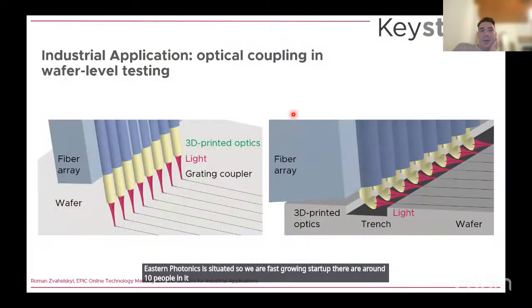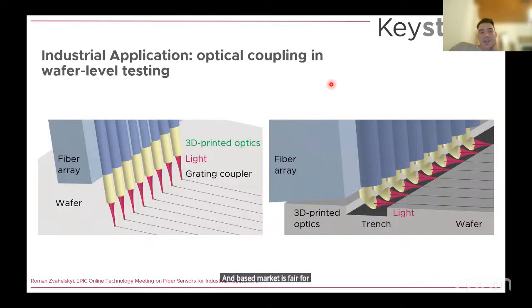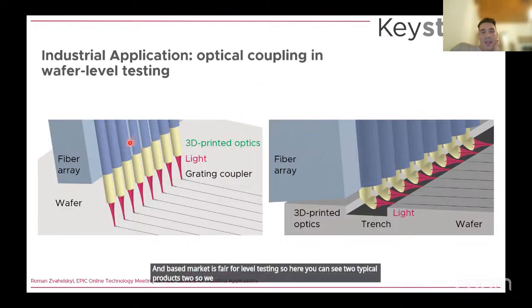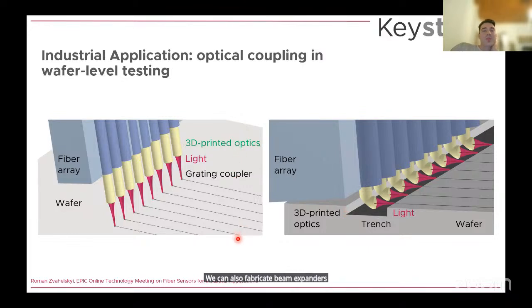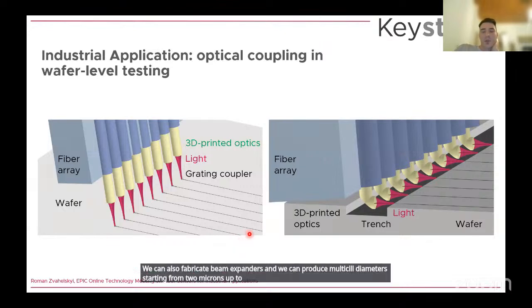Speaking about industrial applications, we provide innovative solutions for optical coupling, and our base market is wafer level testing. Here you can see two typical products. We fabricate lenses on fiber arrays for both grating coupler solutions and for trench coupling, where we can deflect light by 90 degrees or by any artificial angle. We can also fabricate beam expanders, and we can produce mode field diameters starting from 2 microns up to 15 microns.